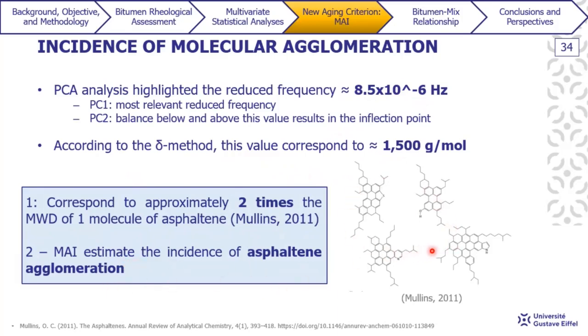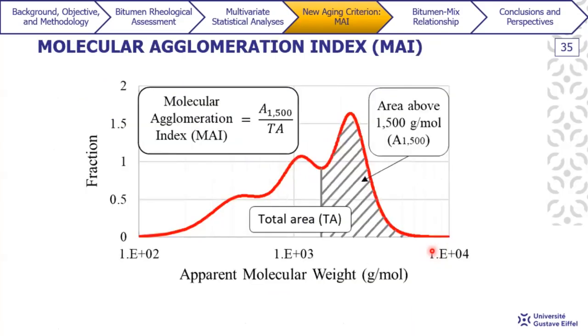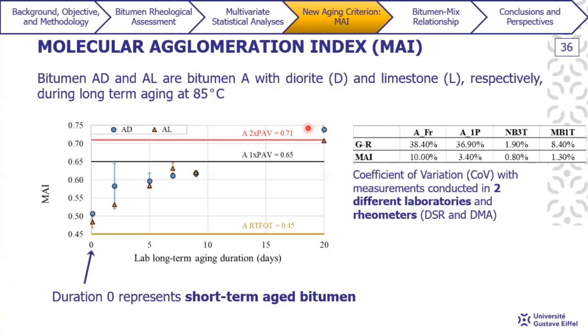Here are just some individual asphaltene molecules, to illustrate. So now we go back to our initial idea, and we define MAI as the area above 1,500 grams per mole divided by the total area. And here we have bitumen AD and bitumen AL. Bitumen AD is bitumen with diorite and AL is with limestone, respectively. In this case, it's just their evolution during long-term aging at 85 degrees Celsius.